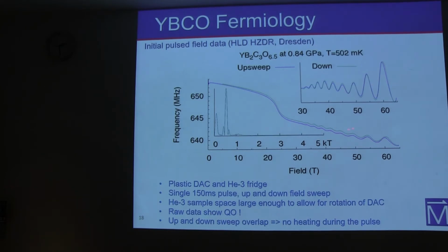So we see here those beautiful quantum oscillations that appear. This transition here, we attribute it to the superconducting to normal transition. So that's the HC2. And so what we do for analysis is that we take the part that shows oscillation, we plot it here with a background subtraction, and then we take the Fourier transform of that part, and this is what we show here.